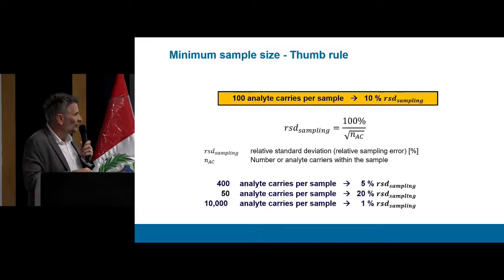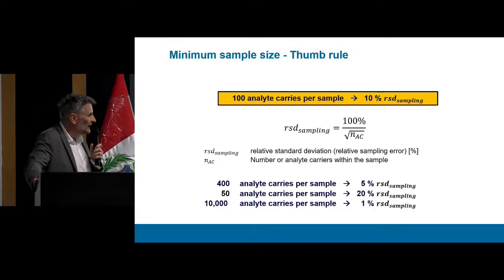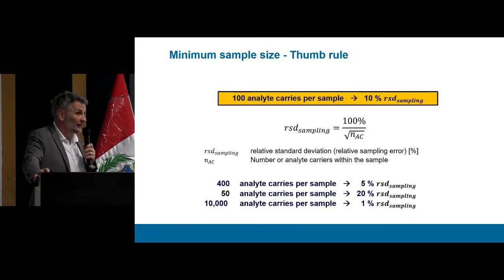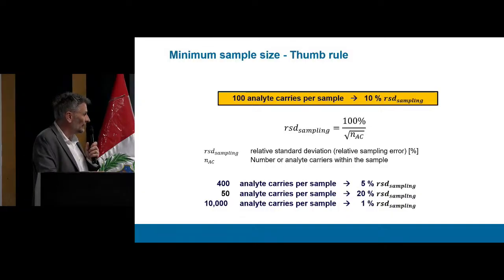If we accept a higher sampling error of 20%, that means we are fine already with 50 particles or 50 batteries in there. If we would like to know the battery concentration with a very high accuracy, with a relative error of only 1%, we would need to take a sample which is really very big, because we need to find 10,000 batteries or 10,000 particles of interest in there. So the relative error we are accepting determines to a large extent the sample size.